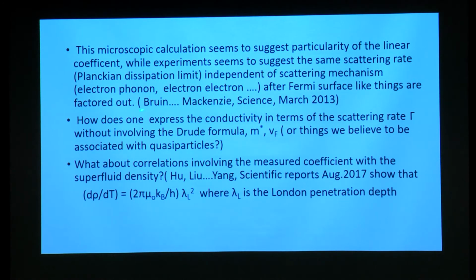This was actually shown in a very nice paper by Bruin et al. in Science in March 2013. They took many systems and plotted results for many systems, but one particular system in which they carefully looked at things was Sr3Ru2O7. That is another version of strontium ruthenate, in which at temperatures greater than maybe 100 or so, it seems to be an incoherent metal, and the resistivity seems to be linear in temperature. But well below that temperature, it becomes a coherent metal for which you can actually measure quantities like the Fermi energy and Fermi surface. You can find the effective mass and so on.